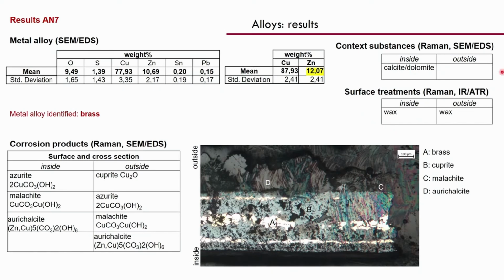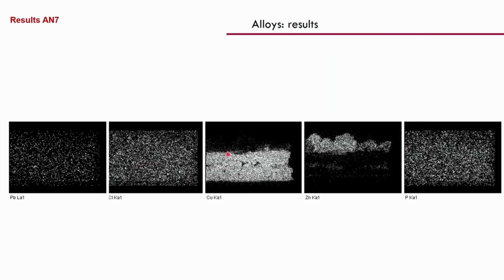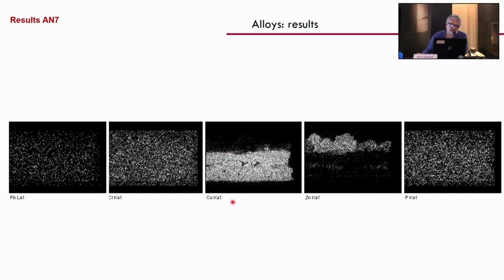So it seems the wax is the main organic material that we identified. As you can see here, there is the mapping, but it's important for us, as we study this kind of materials, to concentrate on the distribution of copper and zinc, because they seem to be separated. You see that here we have copper, and just a little part of the zinc is associated with the copper, but the most part of the zinc is separated. So probably, I don't know, this could be dezincification, a process that can separate zinc from copper in the alloy. But it's something that we have to study more, but it's very interesting to see this situation here.